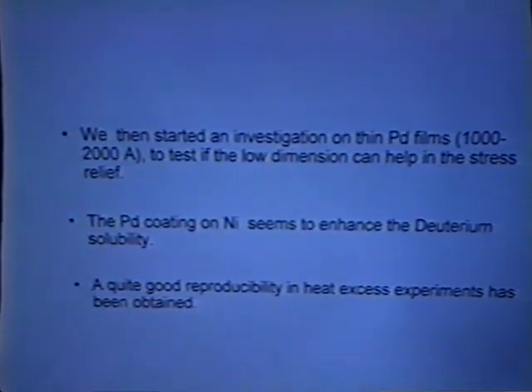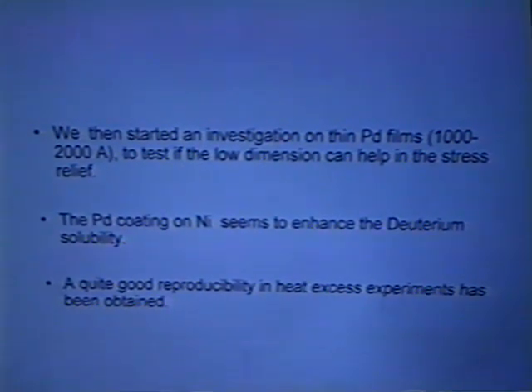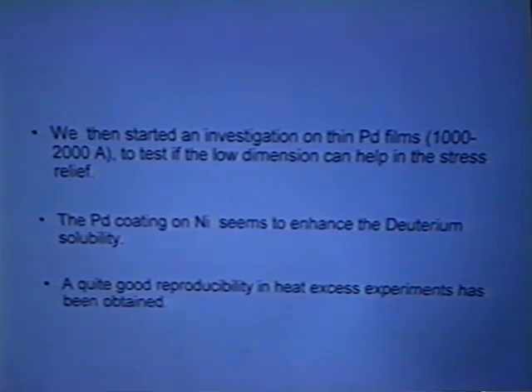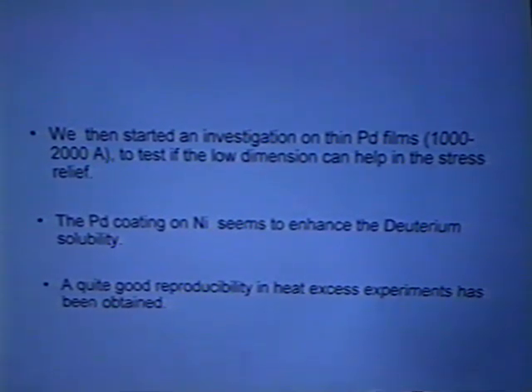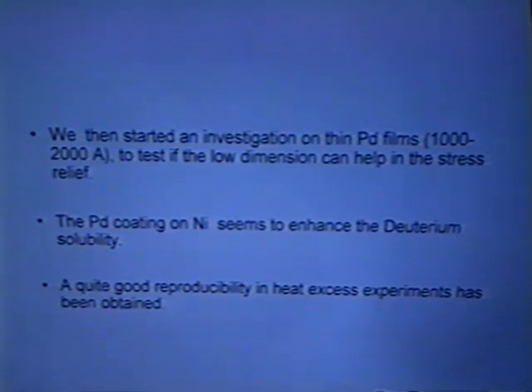What we did then was to move to thin films, and we started to investigate palladium thin films between 1000 and 2,000 angstrom to test if low dimension can help in the stress relief. We coated a nickel plate with palladium by thermal evaporation, and we saw that deuterium can more easily enter the nickel lattice if it is coated with a palladium film.